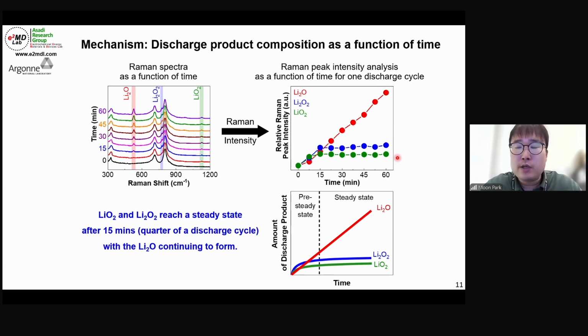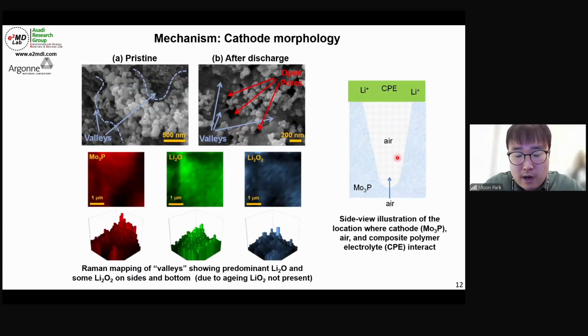So from this point, we tried to understand how exactly everything goes on during the discharge process of the cell with the CPE, the solid state electrolyte. We tried to analyze the cathode morphology, because the discharge products usually grow on the cathode side. From the SEM images, we can clearly see that there is no specific shape of the discharge product. Most lithium oxygen battery research, as I said, has lithium peroxide, Li2O2, as the major discharge product, and it has a very typical toroidal structure. However, in this case, we didn't see anything like that, or any cubic structure.